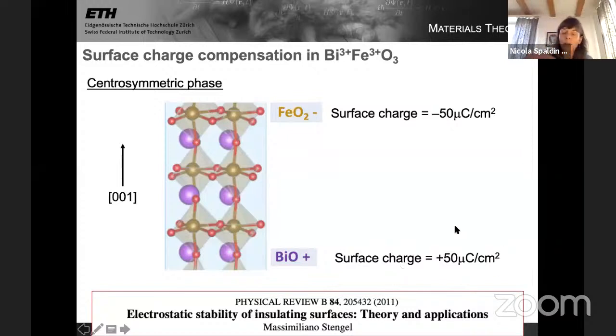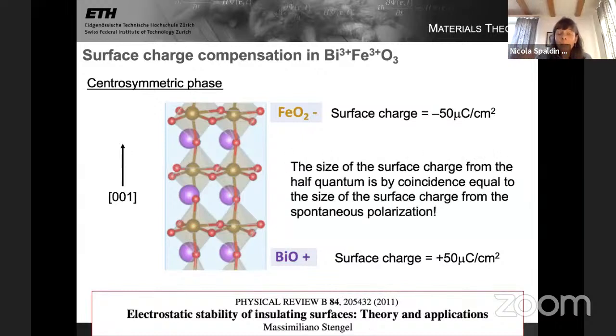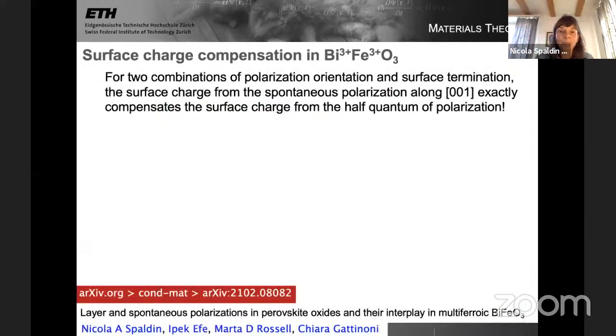And I'm not going to go through the details of how one knows that this surface picks out this value from the centrosymmetric polarization lattice, but I strongly recommend this paper from Max Stengel, which details very clearly how one makes this connection. The important point I want to make is that the size of the surface charge from the half quantum in the centrosymmetric phase, by coincidence, is equal to the size of the surface charge from the spontaneous polarization. So we have a surface charge compensation in bismuth ferrite also.